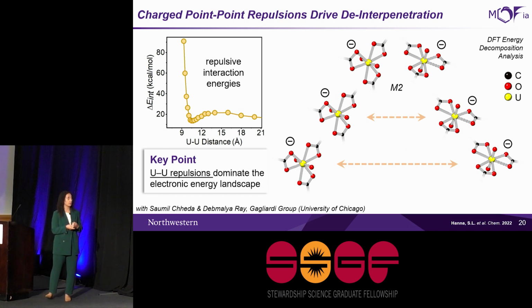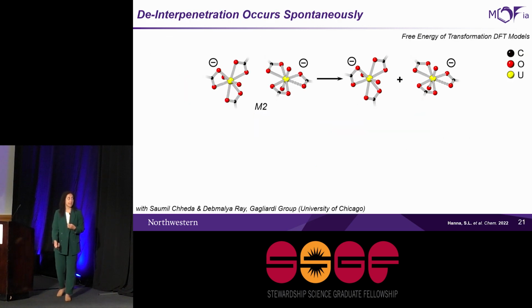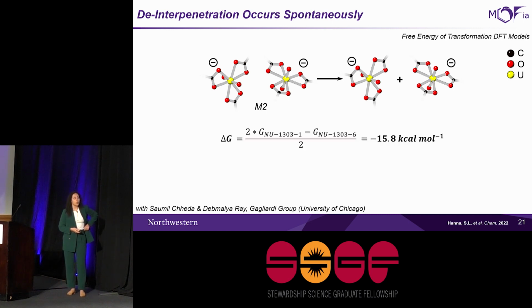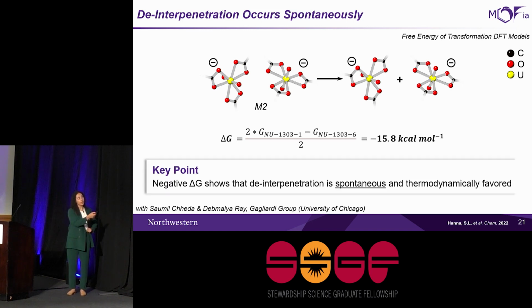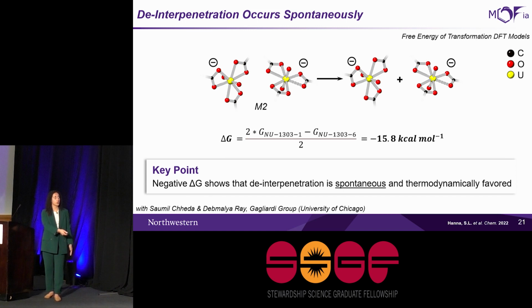driving this disentanglement. Taking this a step further, we also modeled the free energy of this transformation using this equation here, which I won't get into too much of the details, but you can see the important point is that the free energy of this transformation is -15, which is a pretty significant value, showing that this transformation is actually completely spontaneous and happens pretty much on its own without some sort of external stimuli.